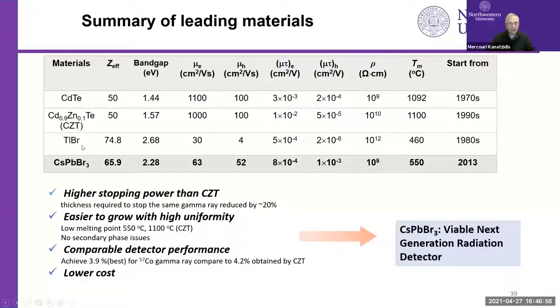Thallium bromide has been a contender for several decades, and it has given excellent radiation response to gamma rays. It has a very wide gap, 2.7. Its mobility lifetime products are a little bit low, but it's improving. However, this material is very soft and it generates defects very easily. And it's not defect tolerant. So the detectors have problems after they are made.